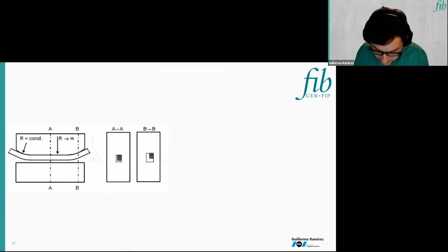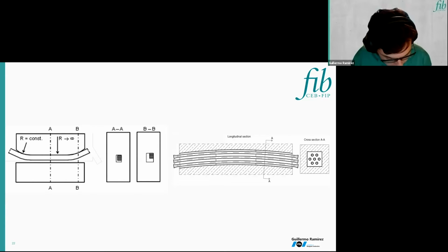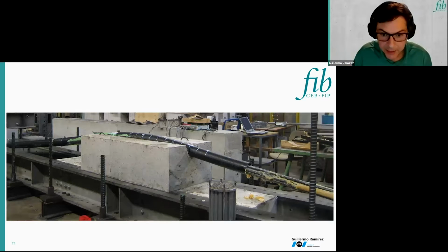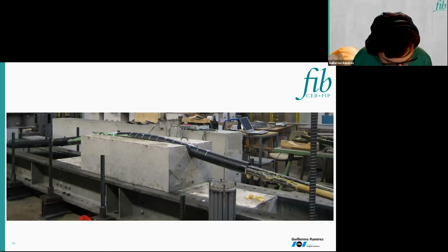For band tendons, box deviators are specially made with rectangular section, typically out of steel or polyethylene. And for monostrand bundles, matrix deviators are cast in the concrete with tubes to individually deviate the strands. All these types of deviators need to be tested to verify the integrity of the corrosion protection barrier after stressing.